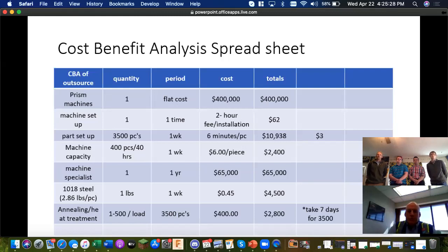And we were also quoted the material cost of 1018 steel is about 45 cents. We were able to weigh our part, and we determined that it weighs roughly around 2.86 pounds. So if you produce 3,500 parts per week, that would cost about $4,500. And for the annealing and heat treating process, we were also quoted. For one load, you can heat treat from 1 to about 500 parts, depending on the size. And there's a flat cost of $400 for that load. So if we want to heat treat 500 parts per load, it would take about 7 days to do the 3,500-part weekly goal.